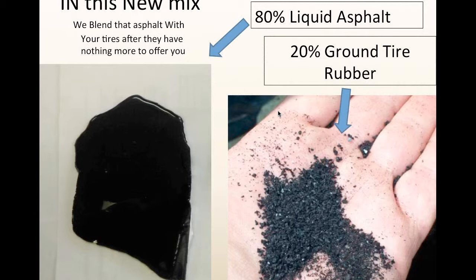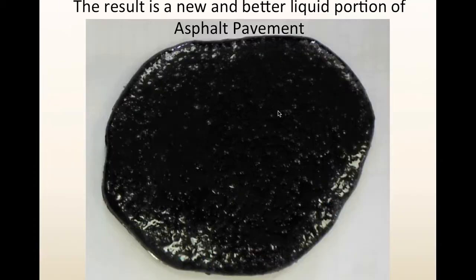In the new mix, the mix that we're talking about today, we're blending 20% ground tire rubber with 80% asphalt. That could be as low as a 90-10 split. The asphalt is the stiff liquid that comes from the bottom of the barrel, and the ground tire rubber is, of course, left over after you've done using your tires. As a result, what we end up with is a really nifty asphalt rubber blend that's a far more flexible and durable liquid. It looks kind of like oatmeal my dad used to make us eat.